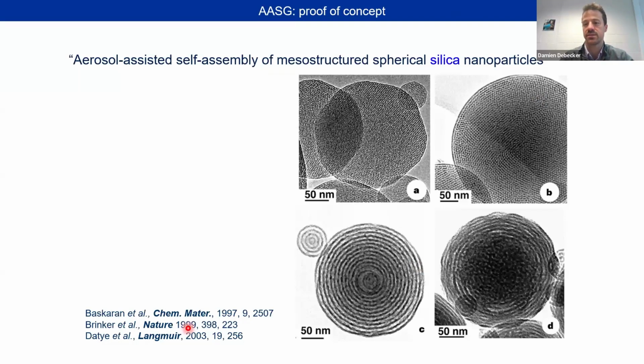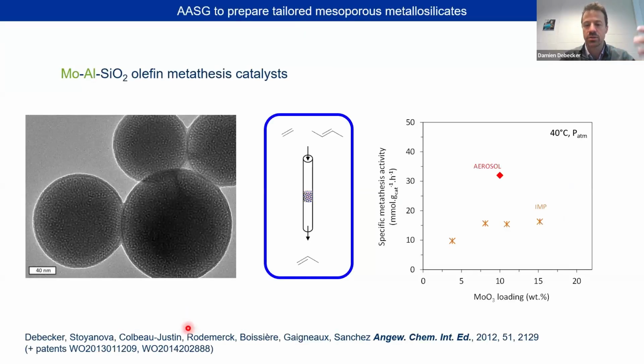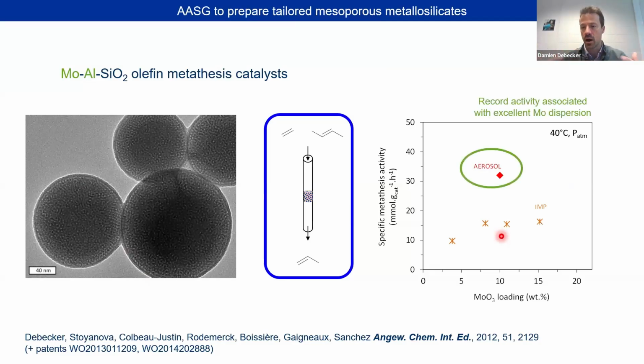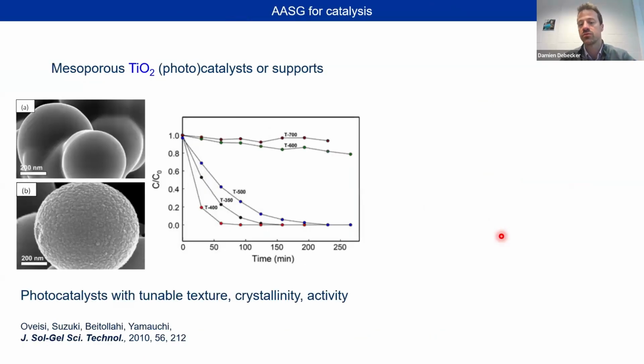Of course, these are not catalysts, it's just silica, well-organized structured silica. We have exploited this a bit later to make very effective catalysts. In this case, it was molybdenum-based catalysts that were outperforming state-of-the-art catalysts made by impregnation because we had a very high dispersion of the molybdenum. And I will talk a lot about silica today, but just for your information, you can work with other oxides as well. For example, here, purely titania materials, on which you can play in terms of texture, crystallinity, and therefore activity. And this was used for photocatalytic applications.